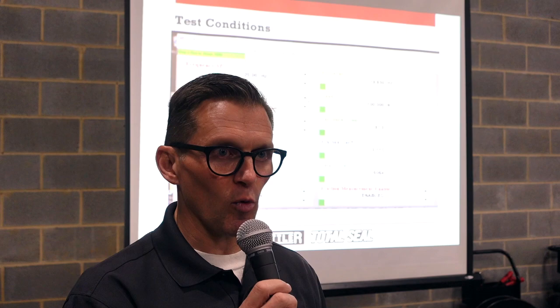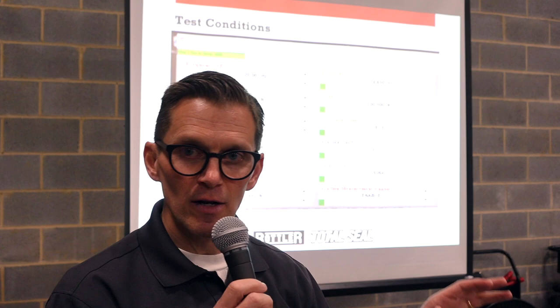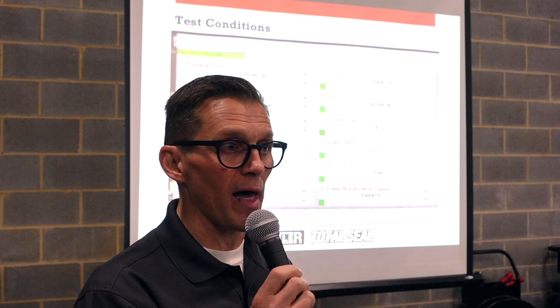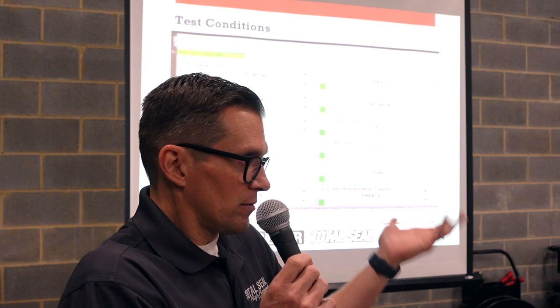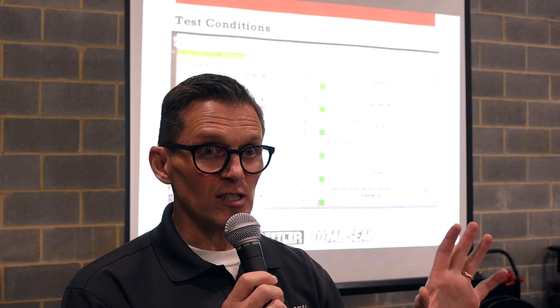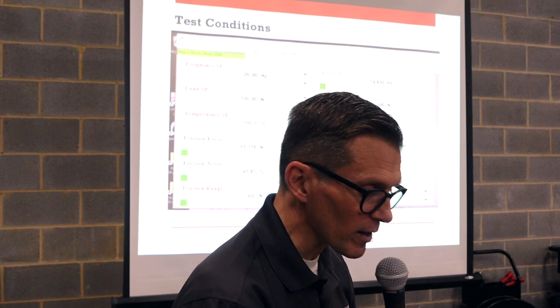So it will actually replicate that same speed, same load, increasing procedure on the cylinder that we did for the camshaft. Because we also noticed that when we did a cam break-in, it would break in the rings perfectly. There was nothing changed after that. So it worked out pretty good. Even with an engine that wasn't a flat tappet, if you treated it the same way, it worked out pretty good.